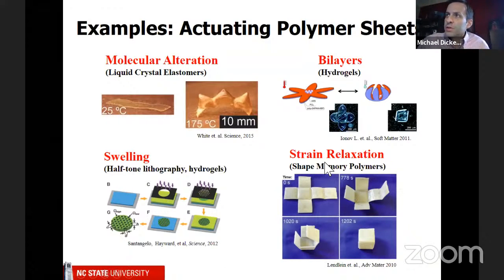And then there's another approach, which is called shape memory polymers. And I'm actually going to be talking about this today, but in a different way than is conventionally done. So with a shape memory polymer, you start with the shape that you want, which is the three-dimensional shape. In this case, it's a box. And then what you do is you heat the material and you stretch it to some flat state. So you start here and you stretch it and heat it, and then you cool it down so that it stays in this shape. Then when you heat it back up, the stresses that are built into those materials will cause it to fold.